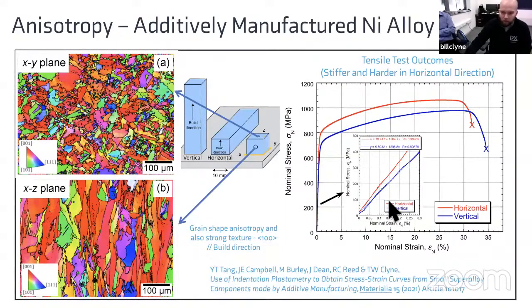What we can see on the right-hand side is that this texture leads to quite significant anisotropy between the horizontal and vertical direction. The horizontal is the in-plane direction, and the vertical is the build direction. If we zoom in on the elastic region, the material is stiffer in the transverse direction than it is in the build direction, and that is because of the 100 texture. So it is less stiff in the 100 direction.